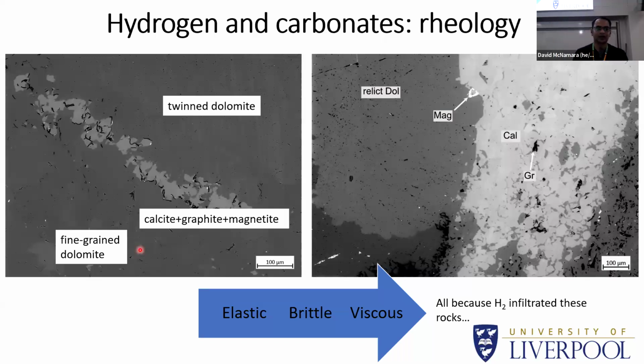So we basically go from a dolomite aggregate that was fine by itself. Suddenly, a bit of hydrogen came in and started destabilizing it. It formed calcite, and there's still a bit of dolomite. These calcite horizons started widening, and then you created a rheologically weaker phase from a rheologically stronger phase. That transitions from brittle fracturing to viscous flow, all because you have some hydrogen coming into the system.